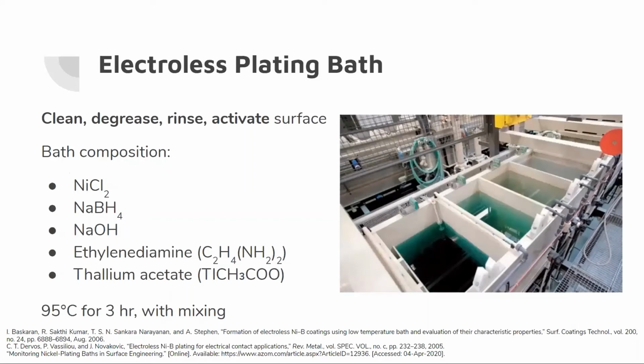Thanks, Jobey. So when we look at the surface of the component, we must perform the following 4 steps before we can actually plate. The first is to clean the surface mechanically by scrubbing. The next is to chemically degrease using acetone. After this, we need to rinse with distilled water, and then we need to chemically activate the surface with either HCl or a Woods or Watts bath to make sure that we can actually deposit our material onto the surface of the ring.